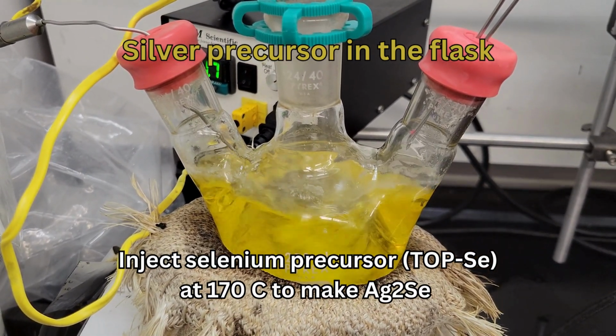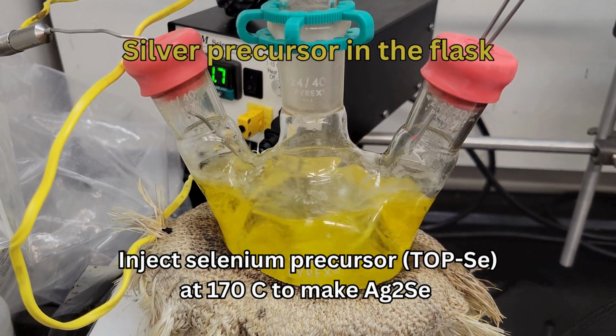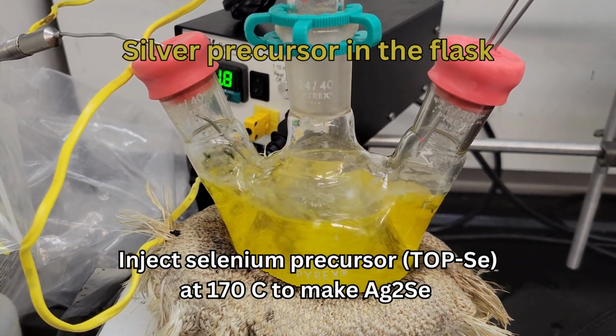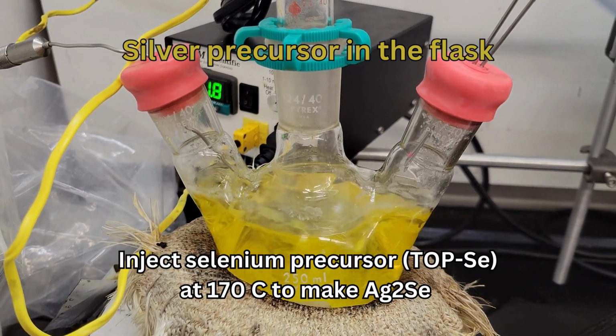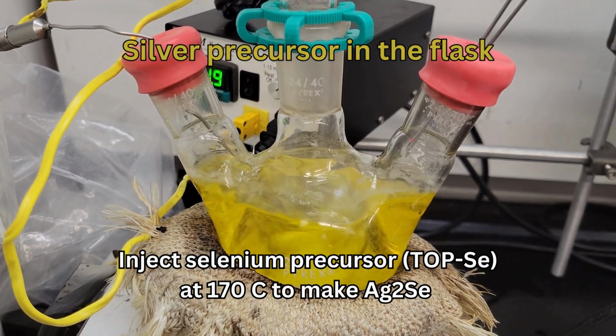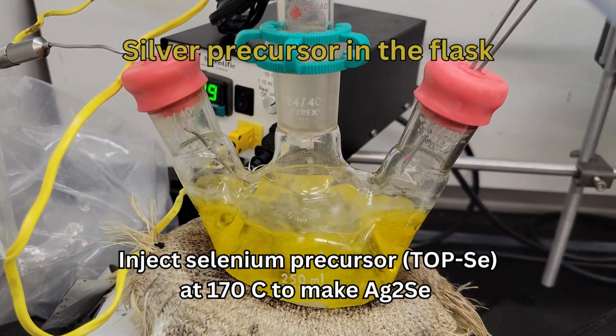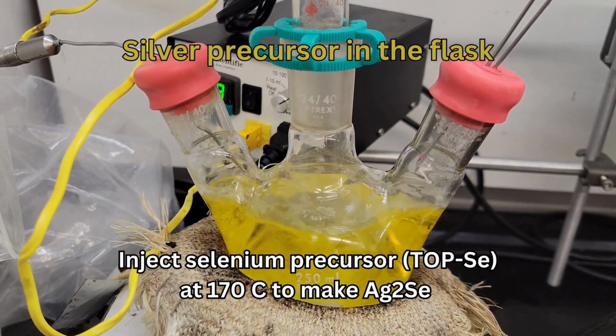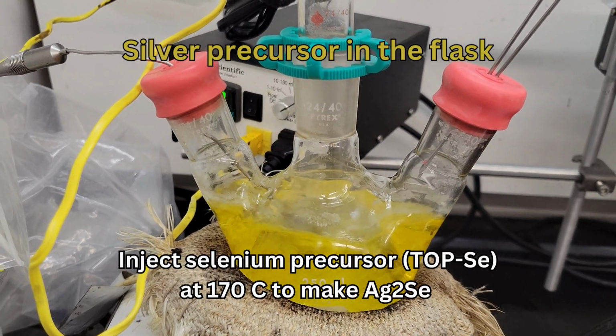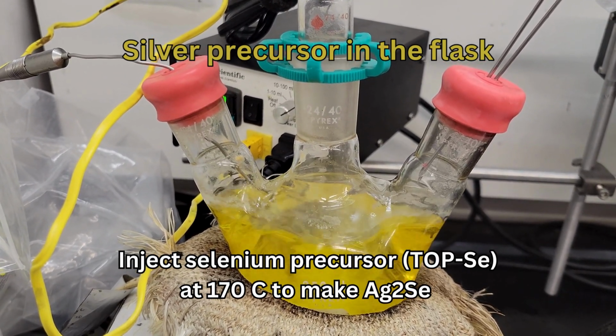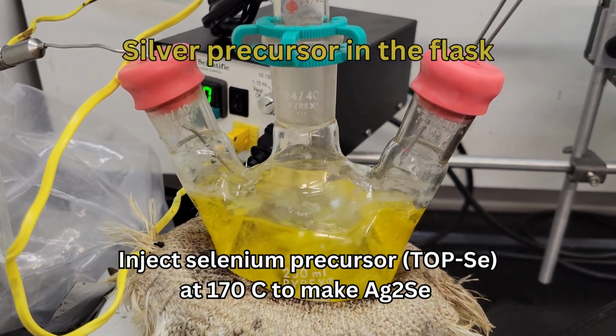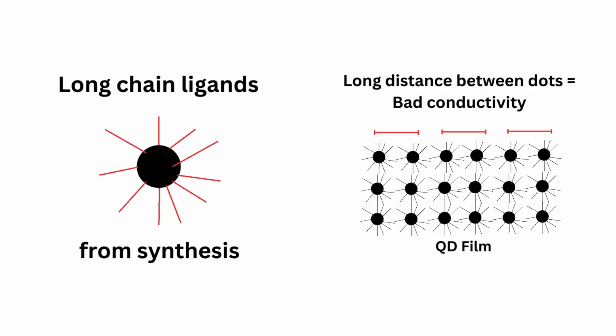We use the hot injection method, which involves injecting a precursor solution of one metal into a heated flask with another precursor in it. For silver selenide, a selenium precursor is injected into a heated silver precursor at 170 degrees Celsius. This method allows for a synthesis that produces uniformly sized quantum dots, which is important for ensuring effective light detection. The synthesis also coats the dots in long-chain ligands that allow them to stabilize while in solution. These ligands are good for ensuring that the dots are stable during synthesis, but they do interfere with electrical conductivity because of their size. The distance between dots is quite large with these ligands, so forming a good film with the dots as synthesized is difficult.